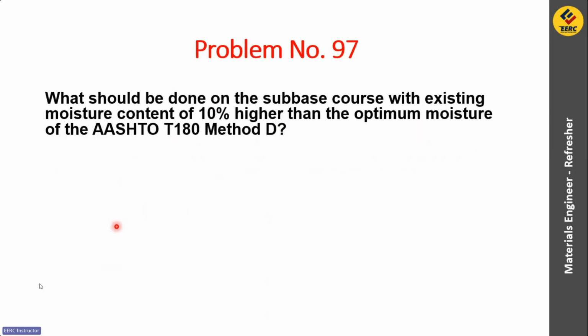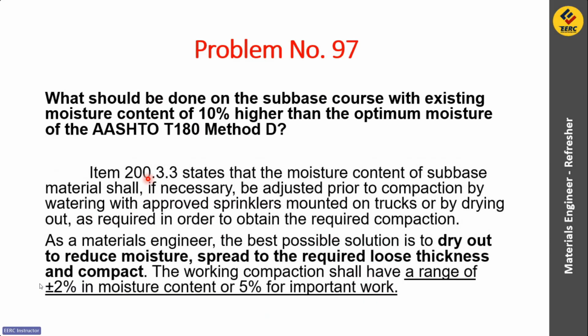Okay? So take note of the statement dito, no? 10% higher than the optimum moisture content. Okay, so kailangan i-dry out. Then item 200.3.3 states that the moisture content of sub-base material shall, if necessary, be adjusted prior to compaction by watering with approved sprinklers mounted on trucks or by drying out as required in order to obtain the required compaction. So as a materials engineer, the best possible solution is to dry out to reduce moisture, spread to the required loose thickness and compact. So itong statement na to, nasa blue box din naman siya.